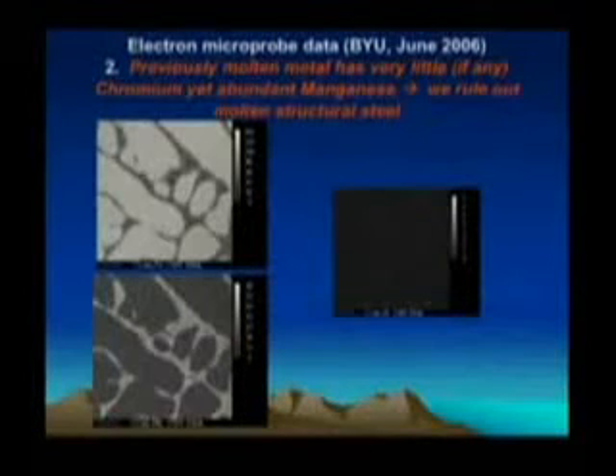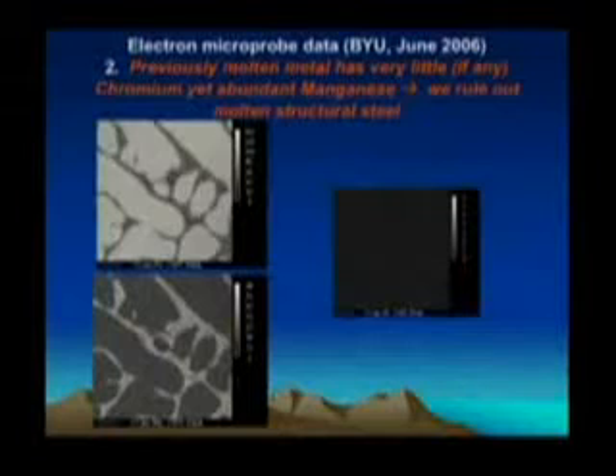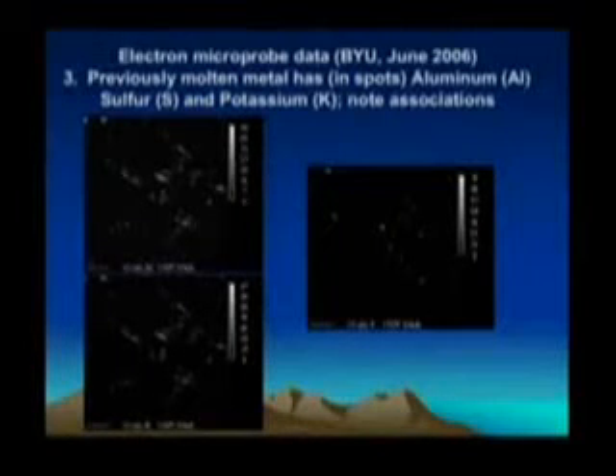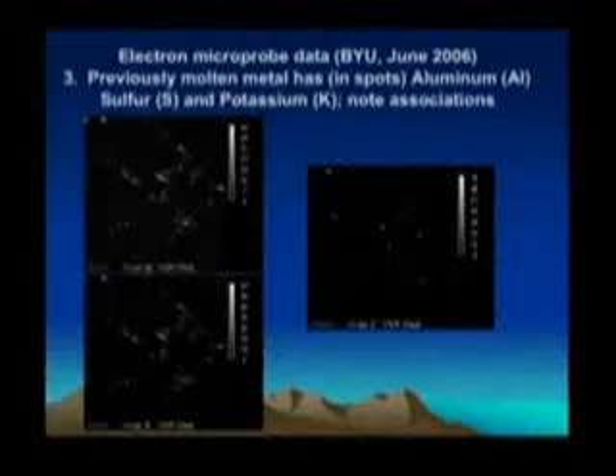The white regions, more iron, but then there's less manganese. And when there's less iron, dark regions, there's more manganese. That's an anti-correlation, which suggests that the manganese is not from steel. It's from something else. Now, potassium permanganate, which has manganese in it, is commonly used in thermites, aluminothermics. Here we see aluminum, upper left, potassium, again, potassium permanganate, you'd expect potassium, and sulfur in spots. So we see all of those. Most of the sulfur you would expect to be burned off, by the way, but there's still some there.